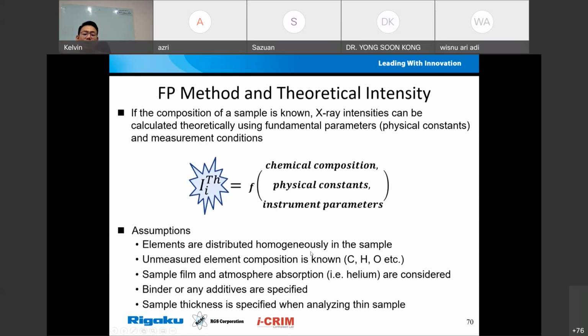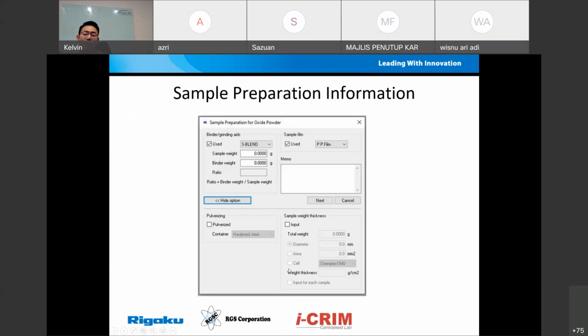The elements are distributed homogeneously in the sample, which is very easy to do. We can just mill the sample and press it, or do the fusion or something like that to eliminate this problem. And unmeasurable element composition, for example carbon, hydrogen, oxygen. Even though we say we can measure oxygen, normally people don't measure it, and also carbon, hydrogen, and nitrogen. So we need to know the composition here, and then we can manually key in this result, or we can use Compton scattering to estimate. And there are also some other options here.